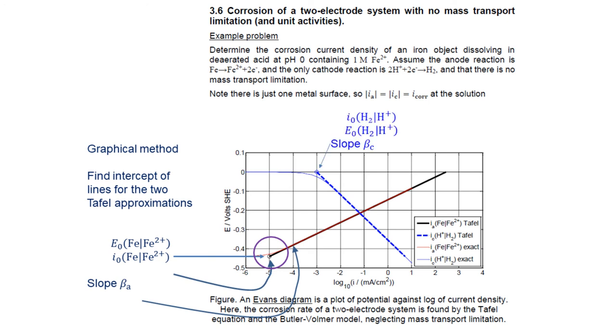Likewise, I do the same for the Tafel line for the hydrogen reaction. So I say that it starts at a point, which is the exchange current density, 10 to the minus 3 milliamps per centimeter squared, and an equilibrium potential of 0 volts. And I draw in a line with a suitable gradient for its Tafel slope, which is given as minus 0.118 volts per decade. And then I see where those intersect. That intercept is the solution. So that's the minus 0.2-something volts SHE as the surface potential, and some 0.066 milliamps per centimeter squared as the corrosion current density. So I could solve the Tafel equations for this case geometrically.